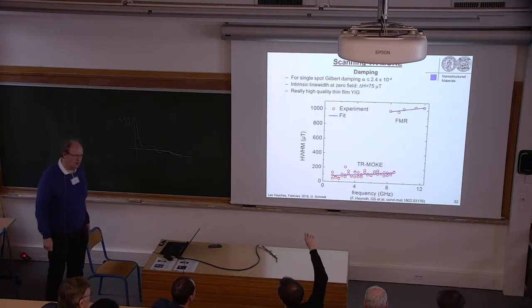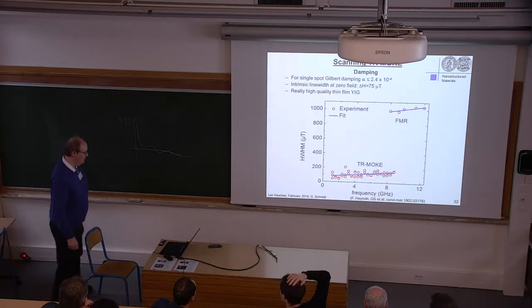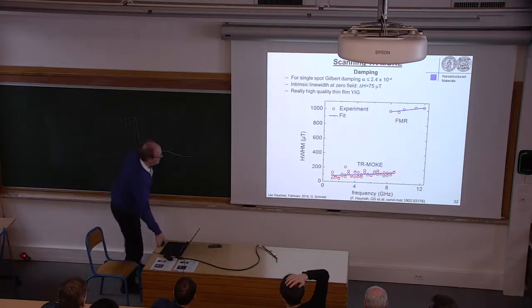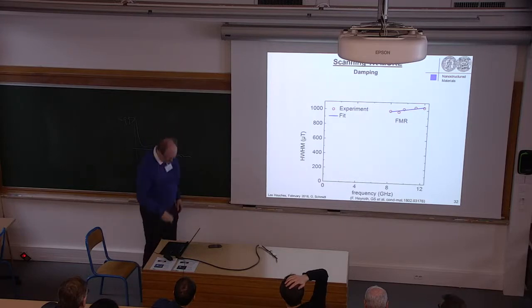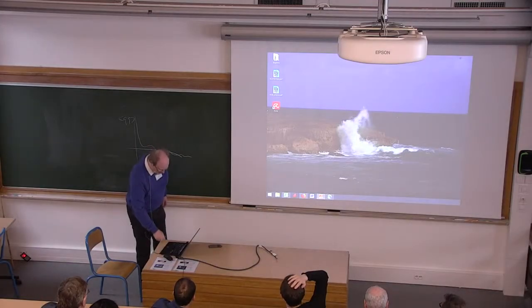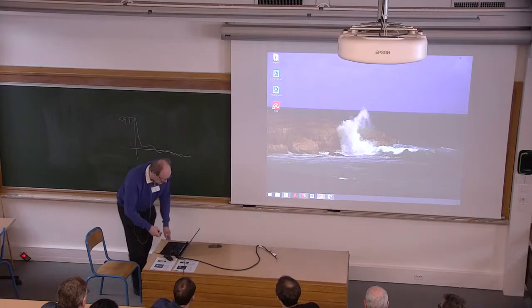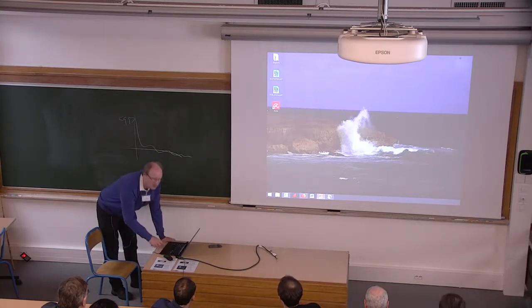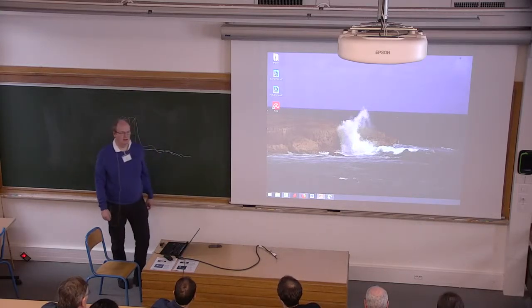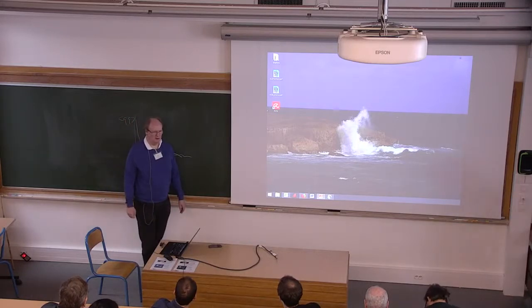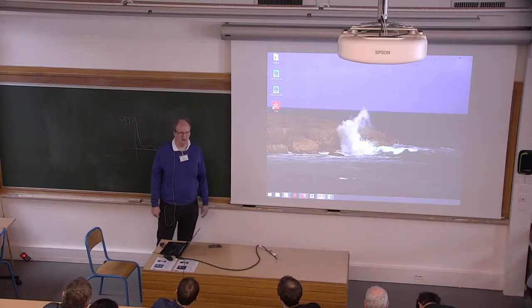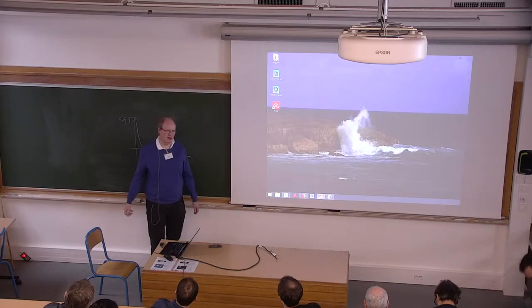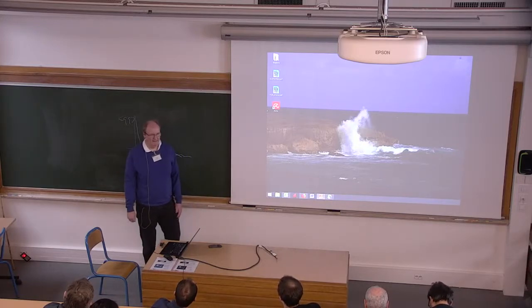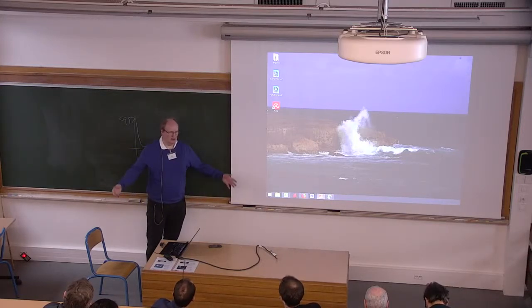What was the thickness of those bridges? I think we are about 100 nanometers probably, but we're basically limited by time at the moment, because the deposition process is very slow, and if we want to deposit 100 nanometers, we take something like 4 hours maybe. But in principle, there's no limitation. We can also grow thicker than this.